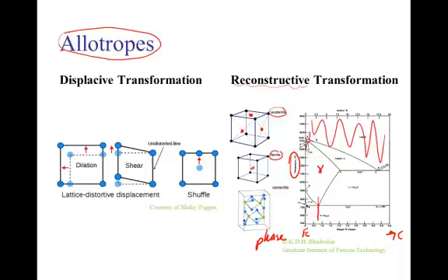In the case of steel, if you cool it quickly, you do not get ferrite. You get a different structure. You get a martensite structure which will remain unless you give it heat and give it time to transform into the structure that it was supposed to be in.